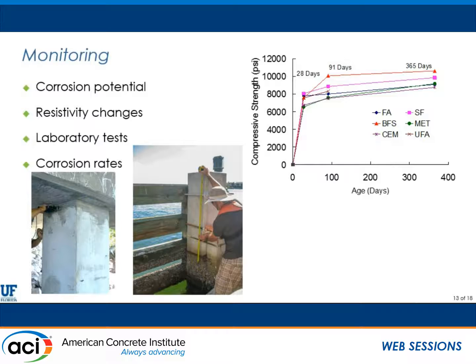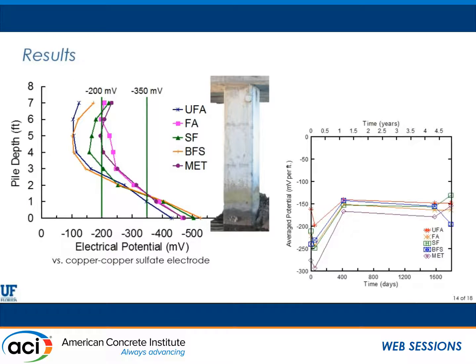Our monitoring program is basically, all we've done up to date is take some corrosion potentials and do some resistivity measurements between the titanium and the working electrode. We've done a bunch of laboratory tests to document the concrete that was used to produce the piles. Those reports have been published and they're posted on the DOT website. We also had the opportunity to do corrosion rates down the road if so desired.